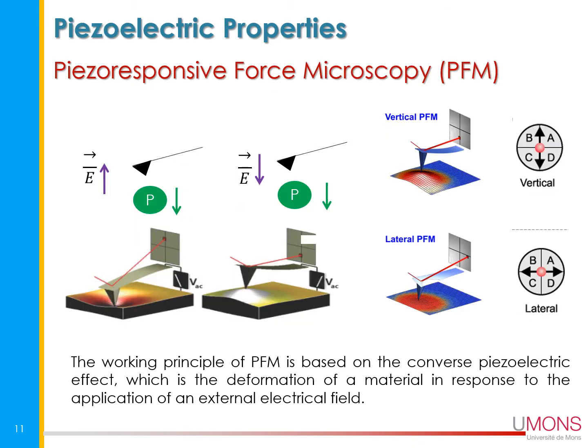For piezo response force microscopy, as I mentioned before, we will use the converse piezoelectric effect in this case. And what we are measuring actually is the deformation when you are applying a voltage between the tip and the sample. And we can measure either the vertical PFM signal or the lateral PFM signal. The problem of this technique for the moment is that it is working in contact mode. And you know that in contact mode, you can sometimes destroy your sample. I will come back later at the end of my presentation to see if we can provide some other technique to be less destructive on the sample.